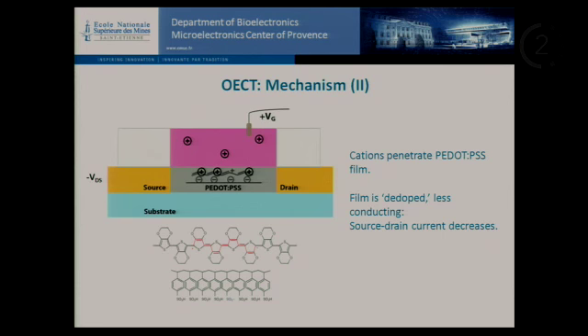Now, if we put a positive charge on this gate electrode that's immersed in the electrolyte, we're encouraging positive ions to penetrate into the conducting polymer film. In order to maintain charge neutrality, therefore, fewer positive holes are needed to compensate these negative charges. These large positive ions are less mobile. This means in this state, the film is considered de-doped and is less conducting. So with the same electric field across the source and drain, we get a lower source drain current.